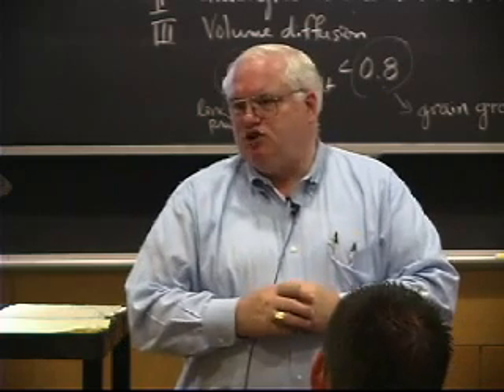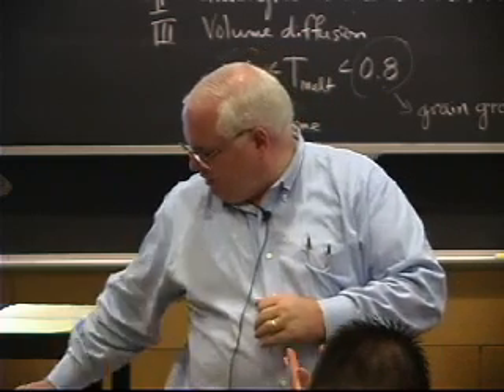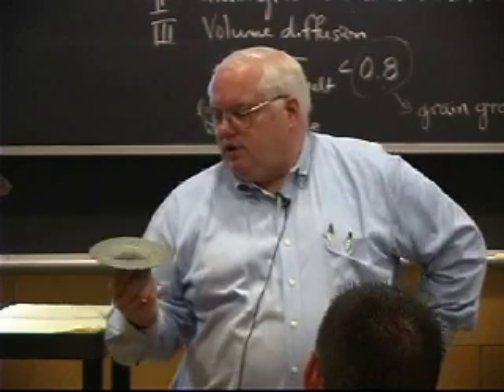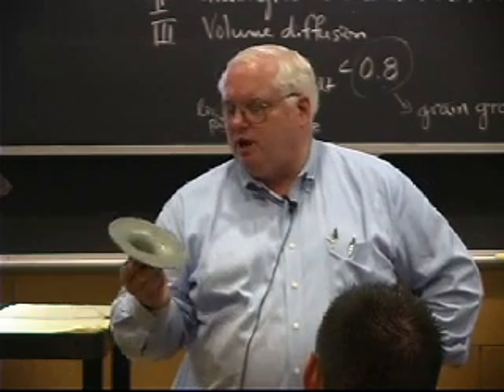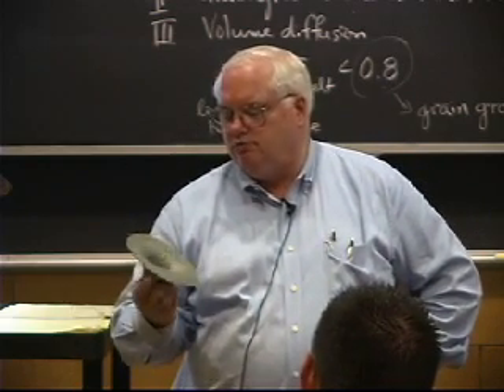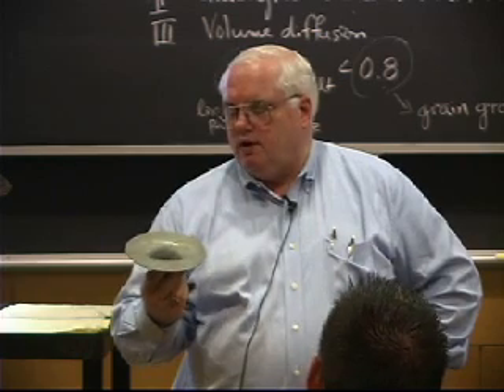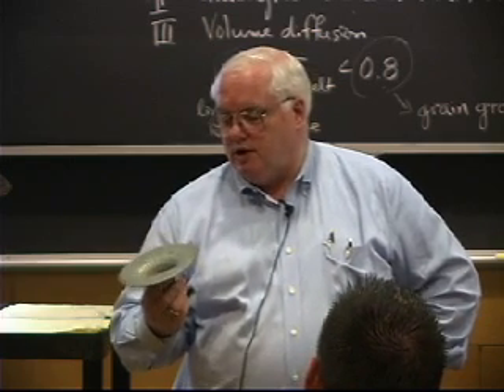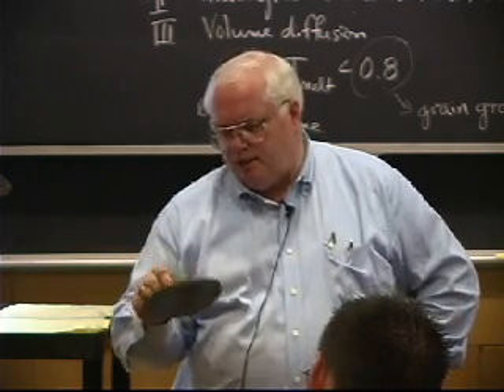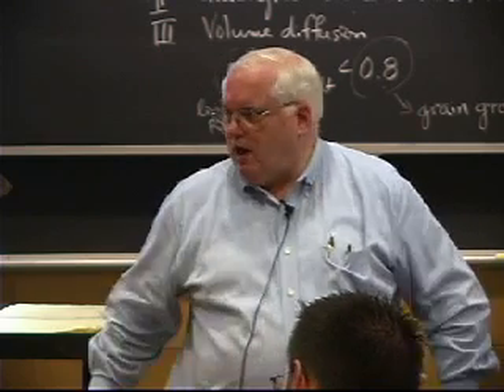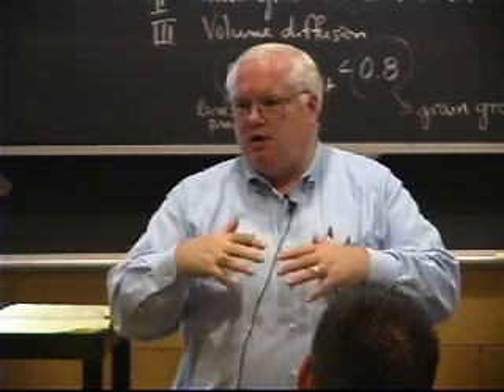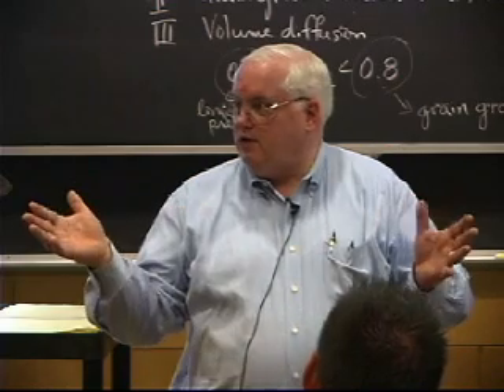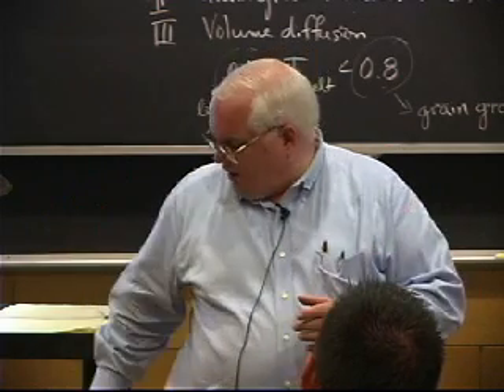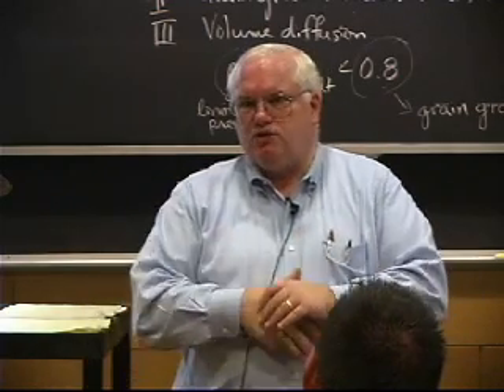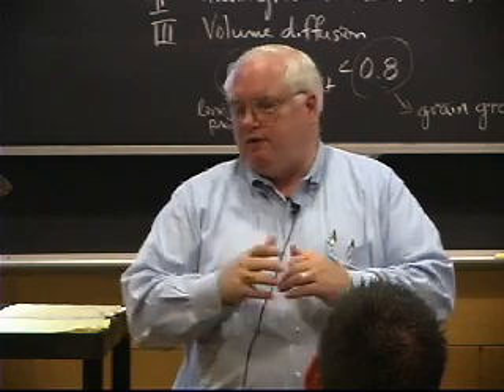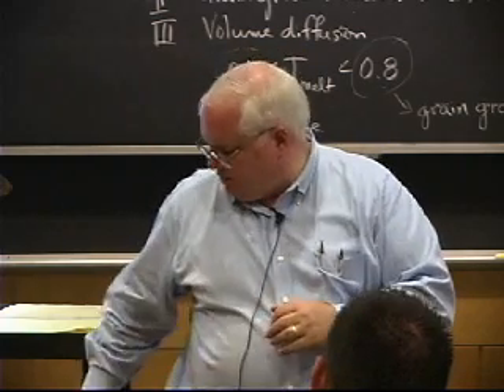So that's superplastic forming. Well, it turns out the Air Force was doing isothermal forging in the late 70s, early 80s, and it's quite widely used for titanium alloys now. But then in the mid 80s, they said, well, I can do more complex parts, and I can diffusion bond them at the same time, because titanium diffusion bonds easily. And so you can make very complex structures with clever fixturing by doing superplastic forming and diffusion bonding.